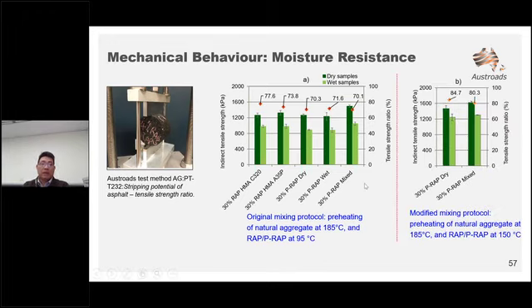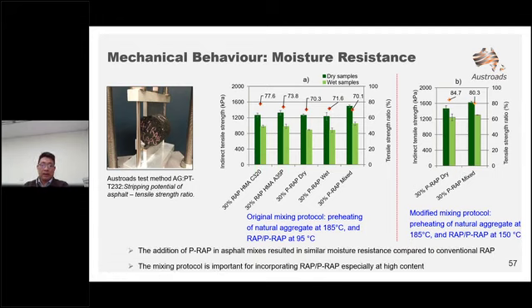So after that, we decided to increase the mixing temperature by increasing the preheating temperatures of RAP and PRAP to 150 degrees, and we found that the tensile strength ratio increased to 80 and 85% for the 30% PRAP mixed and 30% PRAP dry. So it means that the mixing temperature is very important when we incorporate a high percent of RAP and PRAP. And the result in this moisture resistance test also indicates that the addition of PRAP resulted in similar moisture resistance compared to conventional RAP.